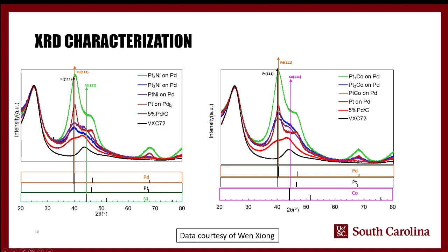But then when you start adding platinum, you see the platinum peak build, and when you add the nickel as well, what we don't really see is the formation of a pure nickel phase. And so what that tells us is that we're not forming monometallic nickel sites anywhere. We're actually getting a bimetallic metal deposited. So you can see there's a lack of a nickel peak here.